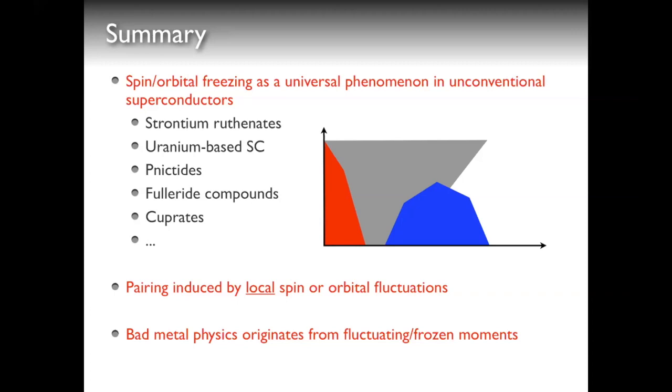There is a very large number of very small mini gaps that are opened due to the distortion of the system, and this in itself already blurs the standard Drude behavior of the optical conductivity. And that is a very robust conclusion, which is already there just at pure DFT LDA level. As a result, I think one should be a little careful, but probably Philip, you agree with that, over-interpreting the 1 over square root of omega optical conductivity in the ruthenates. That's all I think we wanted to point out here.